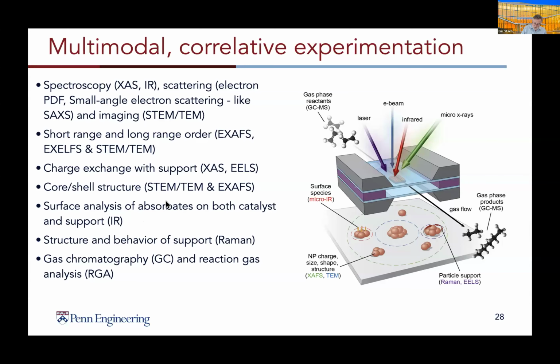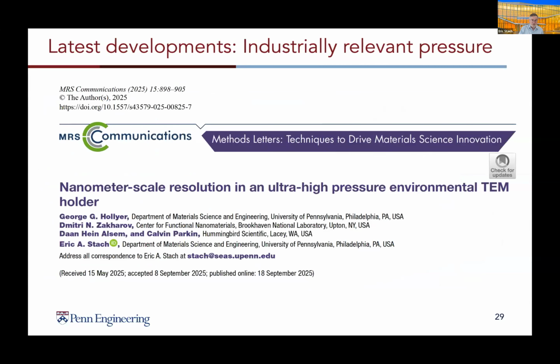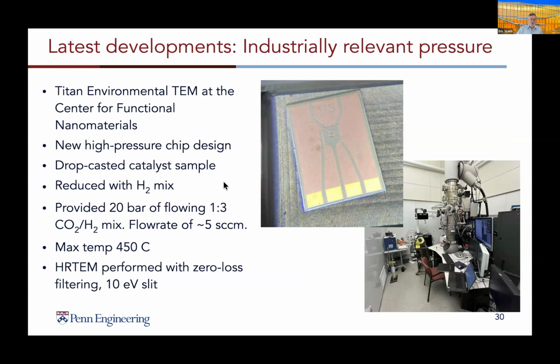Maybe one final thing that's relatively new and I think quite exciting is that working again with Hummingbird Scientific, we've developed a new holder that will allow us to go to extremely high pressures. In this case, we're able to demonstrate up to 450 degrees Celsius, 20 bars, that's 20 times atmosphere, in this case of CO2 to hydrogen.